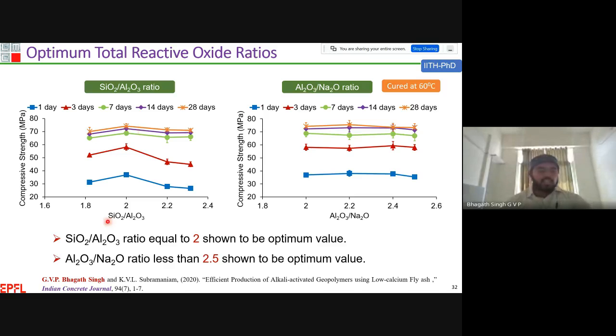And you can see the increase in the ratio from 1.8 to 2 clearly enhanced the compressive strength. But with an increase in the ratio beyond 2, there is not much improvement in the strength after 7 days. We can see a reduction in the compressive strength at early stages, at 1 day as well as 3 days. But after 7 days, there is not much improvement or reduction in the compressive strength when increasing the ratio beyond 2. Thereby, the optimum silica to alumina ratio equal to 2 produces stable fly ash based